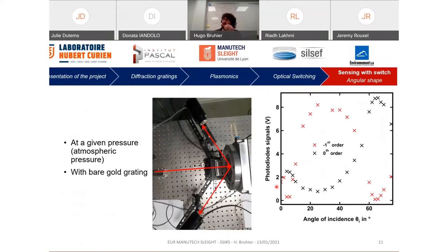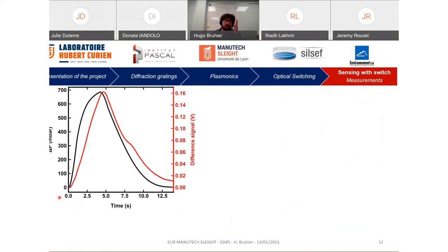And by changing the angle of incidence, we have here experimental measurements of the fundamental order in black and the minus first order of diffraction in red, in reflection always. And here we can see we have our crossing position nearly 55 degrees. So now we put our setup in the angular position of the crossing point, sorry. And now we change the pressure of our chamber.